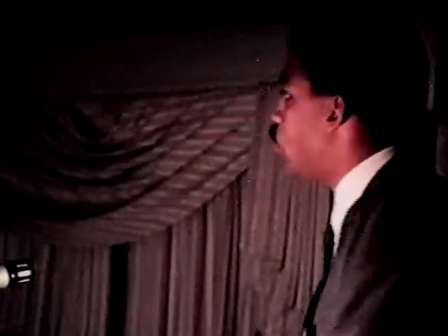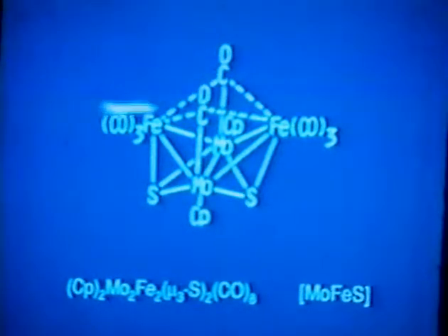For instance, this work focuses on hydrodesulfurization. It's accepted that we want to somehow use a molybdenum-based catalyst. We would like to produce a site that has a promoter. For instance, in this case we have iron. We might also think of using cobalt. The other thing is, from an industrial standpoint, we like to incorporate sulfur so we don't have to pre-sulfide a lot of our catalysts. These are two examples of clusters that were utilized in this work.